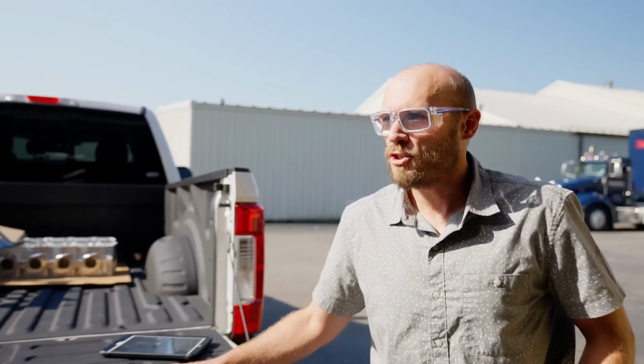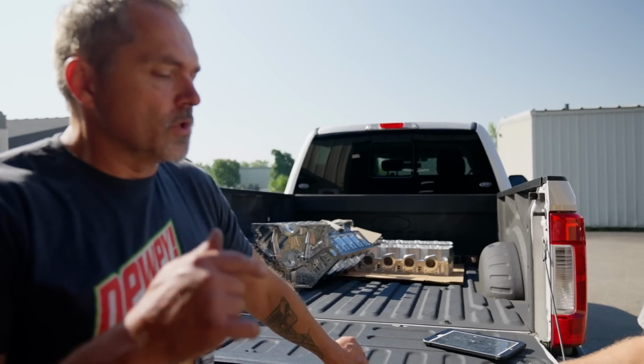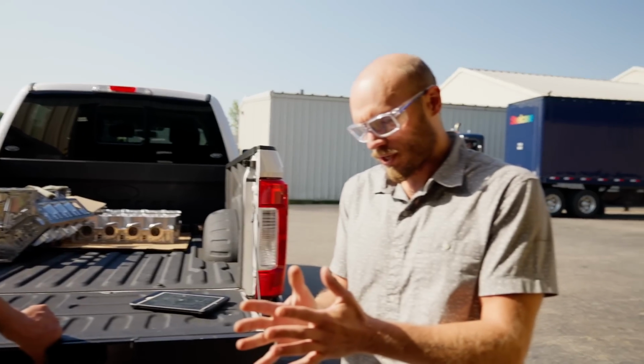So we're roughly looking at 2 thou is the thickness of the actual coating itself. Then you're going to see a growth of about 1 thou per surface. Compare that to a normal anodize. If we were doing a colored anodize, you're talking 6/10 of a thou, so it's quite a bit thicker. So the anodizing goes in a thou and then comes out a thou. Yeah, you're using the base aluminum to make your aluminum oxide, which is what anodizing is. So you're using current and the electrolyte in the tank itself to create aluminum oxide,